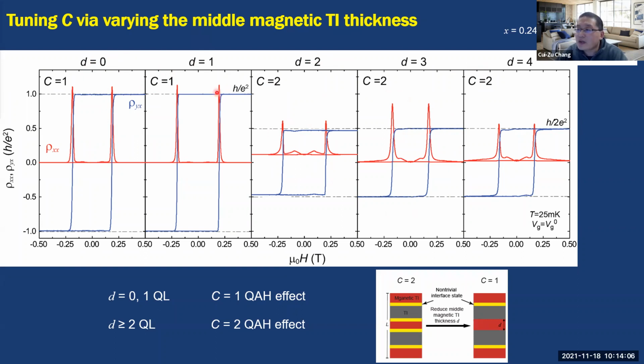We notice that when the middle layer is very thin, the top and bottom quantum anomalous Hall layers share the same topology. They will become one quantum anomalous Hall layer. That's the reason we realize the C equals 1 quantum anomalous Hall insulator. And when the middle layer is very thick, the interaction is not enough. So there are two separate quantum anomalous Hall insulator layers here. That's the reason we could realize the C equals 2 quantum anomalous Hall insulator.